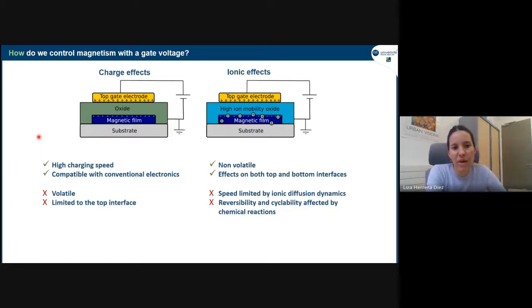So then let's remember that we have a metal, and then this will be very, very much concentrated at the top interface. And then we know, for example, in the type of materials we want to work with, the interface with the substrate is very important, because most of the time we have a heavy metal substrate, which gives us effects like DMI, and then it's important for spin orbit torque. So it is important to be able to access the bottom interface, which we cannot do with charge effects.